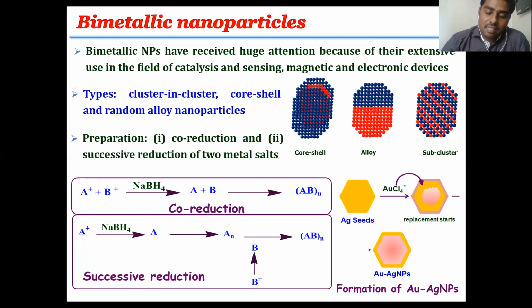Of course, metal nanoparticles are ideal for electrocatalytic applications, but their properties can be tuned by combining with another metal nanoparticle to form bimetallic nanoparticles. The combination of two metal elements as bimetallic nanoparticles creates superior properties, and bimetallic nanoparticles have received great attention because of their extensive use in the fields of catalysis, sensing, magnetic, and electronic devices. Bimetallic nanoparticles are of the types cluster-in-cluster, core shell, and random alloy nanoparticles. In random alloy nanoparticles, the two metal elements are placed randomly, and in core shell nanoparticles, one element forms a core and the other metal forms a shell to form a core shell metal nanoparticle.